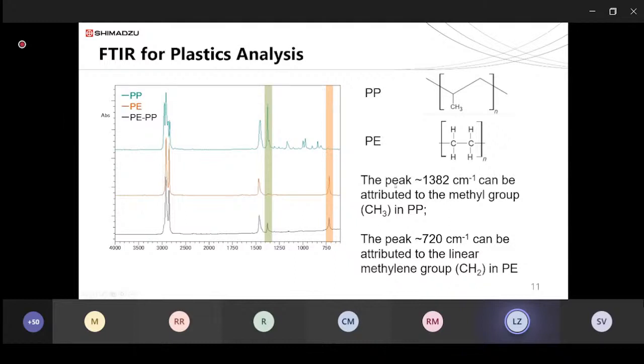In fact, we are able to find a peak at around 1382 reciprocal centimeters. And if we look at this peak in the green curve, it is obviously visible in the PP, but it's missing in the orange curve, which means the peak for methyl group can serve as a signature to tell these two species apart. And similarly, in PE, we have a unique peak at 720 reciprocal centimeters, which can be attributed to the linear methylene group, CH2, in polyethylene. And this peak is only visible in PE, but missing in PP.